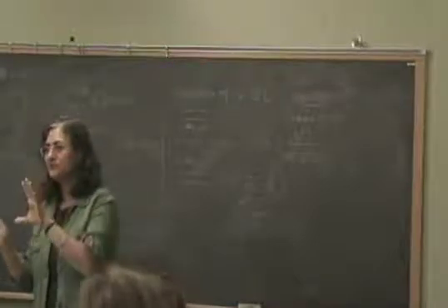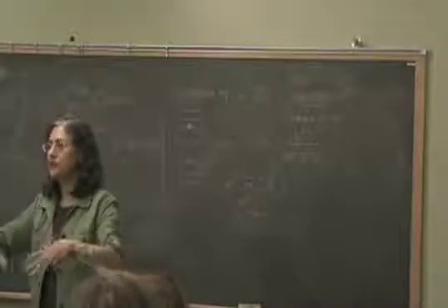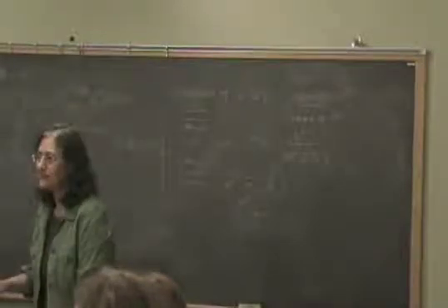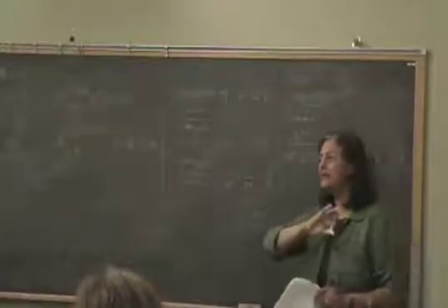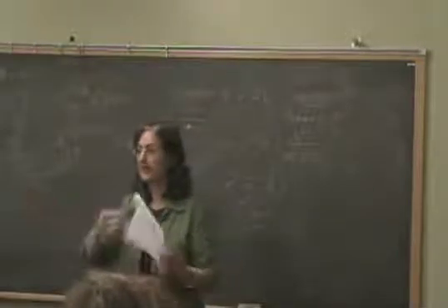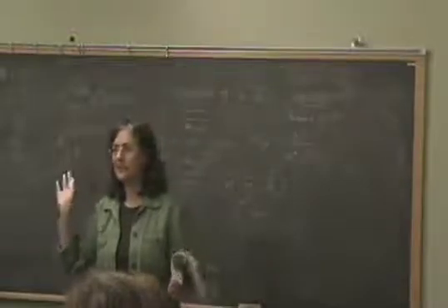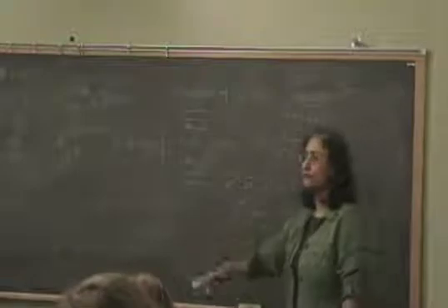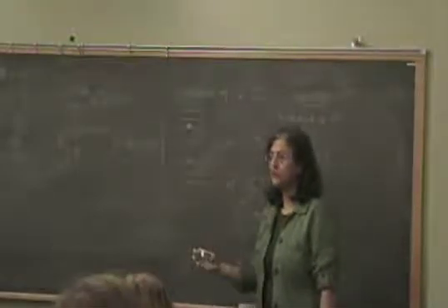But it actually has to be questioned. This entire picture of effective masses and everything has to be questioned. That's something I'm not going into, but you're kind of assuming that your electron waves are able to travel over large distances when you define these effective masses. So it does have to be revisited. You have to basically solve the entire structure of eigenvalues for the dot.